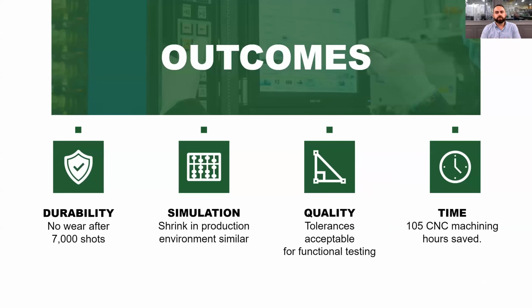We molded 2 different types of material. We molded a PC ABS blend and also a straight ABS. One cavity had over 7,000 shots. The customer was able to use all of those parts for their biocompatibility testing, and the fit, form, and function testing. We found that the shrink was very similar to the production environment. However, we also learned that the overall length of the part was shrinking 20 thou compared to the 7 thou shrink. So that's something we were actually able to address with the production tools.